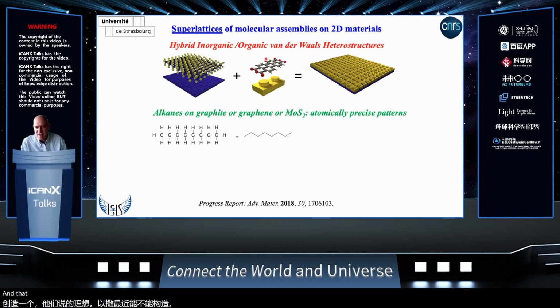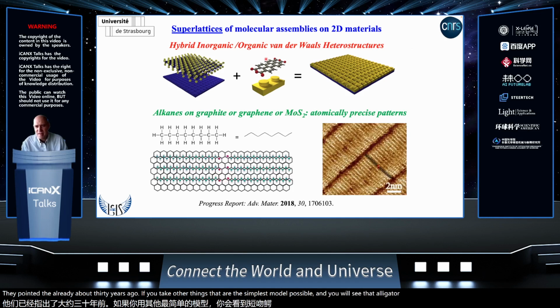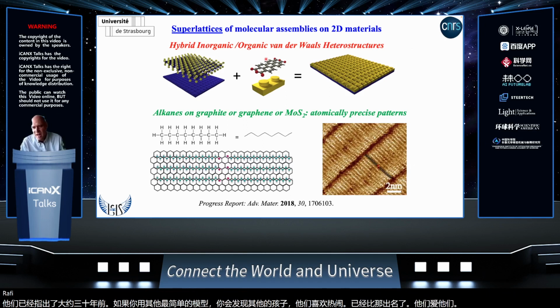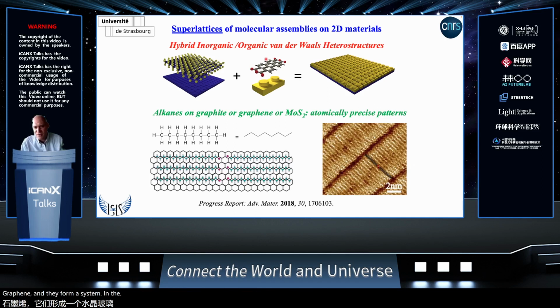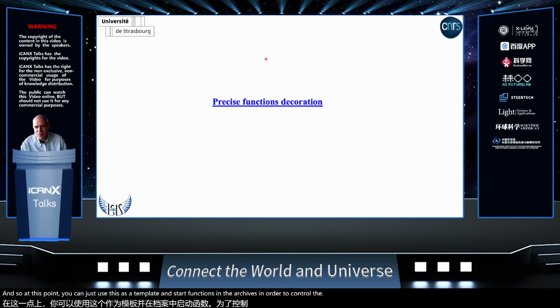That can be done with a very simple chemistry that was reported already about 30 years ago. You take alkanes, which are the simplest molecules possible, and you will see that alkanes love the basal plane of MoS2, they love the basal plane of graphene, and they form crystalline lamella structures. And so at that point, you can just use this as a template and start functionalizing the alkanes in order to control the positioning of functions, so to decorate your 2D materials with functions with atomic precision.